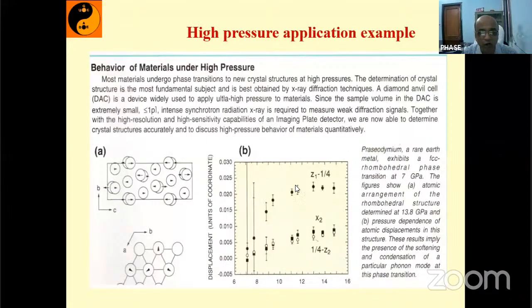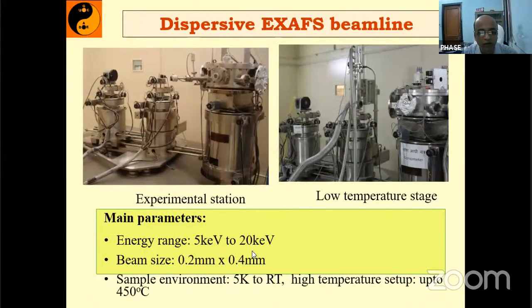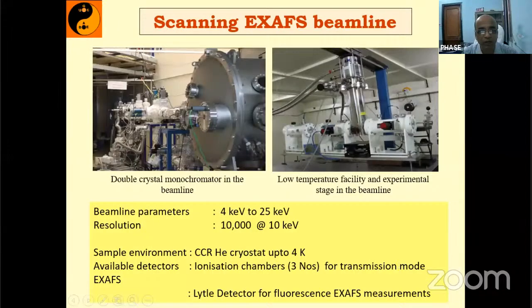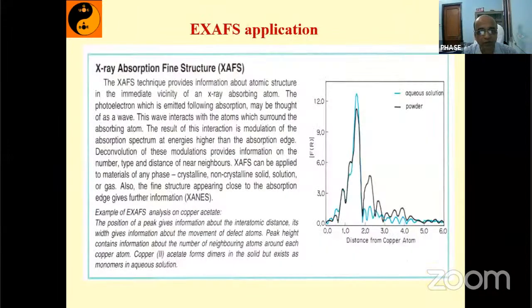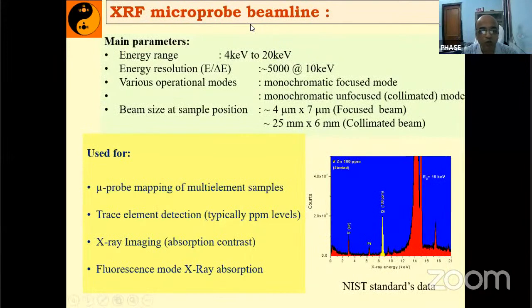Then the EXAFS, which I already told you about for the amorphous, has an energy range from 5 keV to 20 keV. The temperature range is from low temperature up to room temperature. So this is also available. Then scanning EXAFS. This XRF microprobe is for knowing the composition of an unknown sample and what the percentage of each component is.